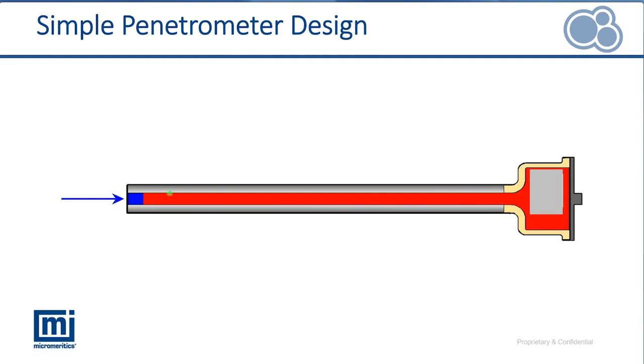The glass I showed when we looked at the penetrometers, the outside glass of this stem area is coated with a metal, and we can tie that to the ground of the instrument, and then we can attach a capacitance circuit to this metal cap that seals the penetrometer. So now we have a capacitor that varies in length as the mercury moves down the penetrometer into the sample. So if we just simply measure the capacitance values without making contact with the mercury, we can then determine the amount of mercury that's moved in there.